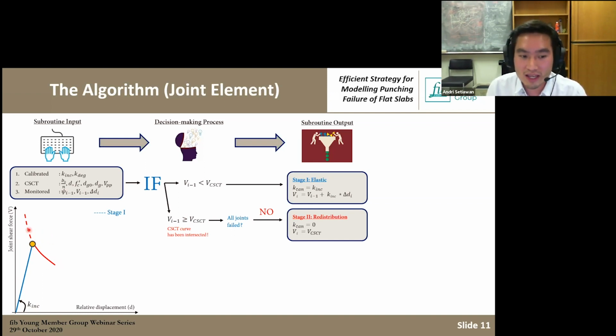So for the joint that has failed, the resistance will reduce, whereas at the same time, the shear will redistribute to adjacent joints where the failure criterion has not been intersected. So that's the idea of how we can simulate the redistribution.